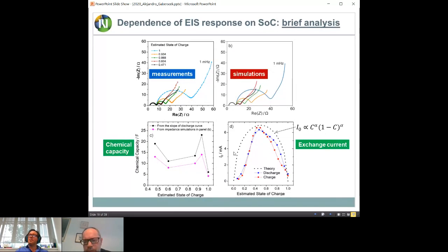The general theory, which is not completely valid for batteries, where we have better theories in the literature, gives the same or a similar bell shape, and you can see that impedance also tells you there is a bell shape. It is not symmetric. That's interesting. We are still working on an explanation of that, but you can extract this kind of data. So with only these two changes, you have all the fitted curves during charge and discharge.